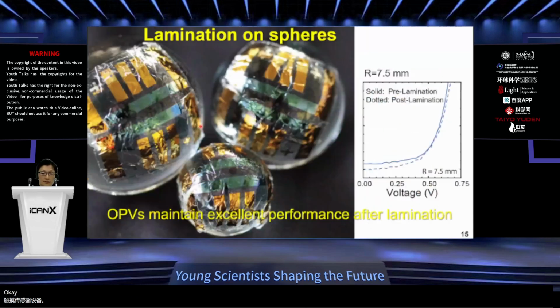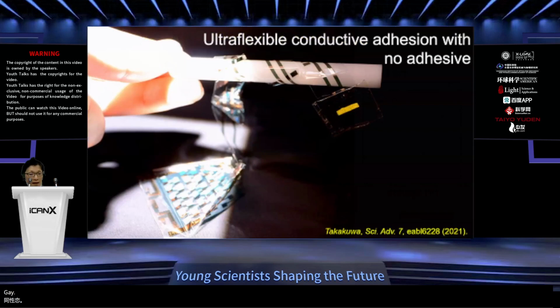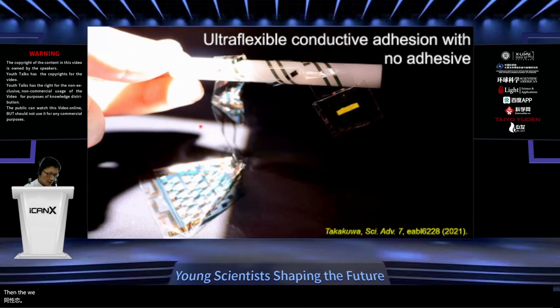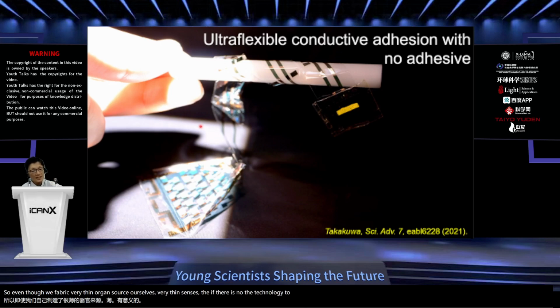Okay. Then next we try to focus on how to make integrated devices. Even though we fabricate very thin organic solar cells and very thin sensors, if there is no technology to integrate them with each other, such an interconnect region loses its flexibility. So we developed a no-adhesive direct conductive bonding method.